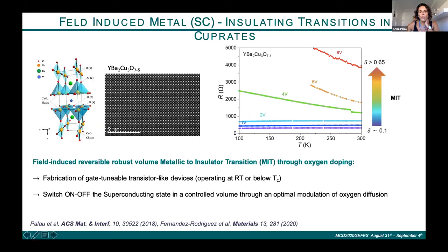The system that I will mainly talk about is YBCO, a cuprate, which is a superconducting material. The YBCO film has been driven from this state, which is close to delta equal to zero, which is metallic above TC and superconducting below TC. This is the initial state where we start with the material, and then we apply voltages in this film, and depending on the voltage that we apply, we achieve different deoxygenation states, states which are underdoped with a certain delta value, which accounts for the number of oxygen atoms that we remove from the system, that drift the system from this metallic to this completely insulating state with a very large difference of resistance.